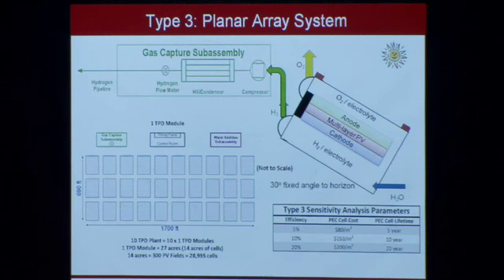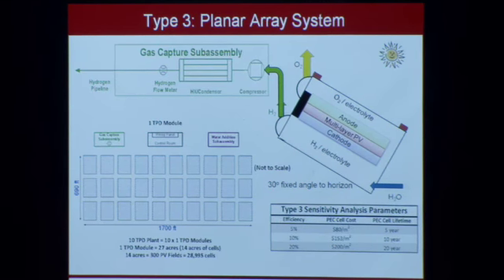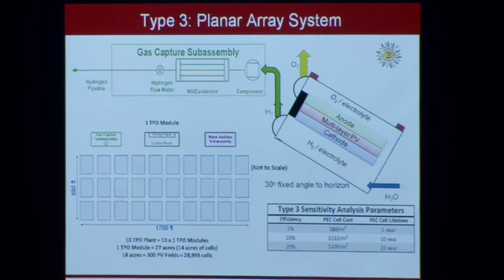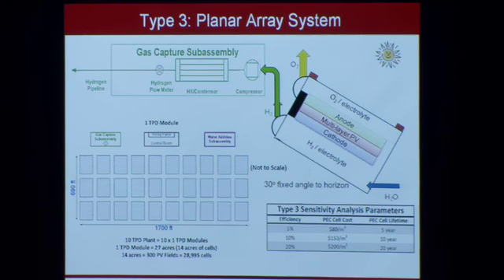This effectively looks like solar cells, just like a solar cell array sitting on a rooftop. They're tilted at a 30-degree angle to maximize the amount of solar photon absorption. I should say that the baseline efficiency here is 10%, $153 per square meter, which basically comes from the CIGS world, and a PEC lifetime, again, we're dreaming here, of 10 years. That material doesn't exist, but these are absolutely possible. If we can do our research and development right, we can ultimately produce these types of materials. We're just not there yet.